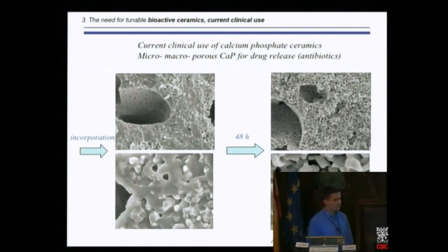We can incorporate drugs. So you can play with these calcium phosphate ceramics by making drug release. And especially what we have made is a simple strategy to release antibiotics. And it's important to release antibiotic at the site where you implant the bone substitute. And you play with the microporosity again. We have a microporous body. So the idea is to impregnate with antibiotic.